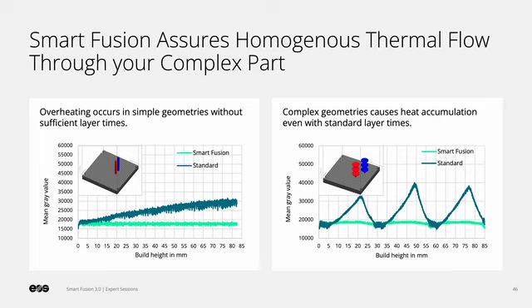As you can see, the mean gray value changes with the geometry in the uncontrolled sample. So to achieve a constant gray value, Smart Fusion needs to initially reduce the laser power as the cone radius grows, but then gradually increase it again after the maximum diameter is reached. This pattern is then repeated again and again for the middle and the top cone.